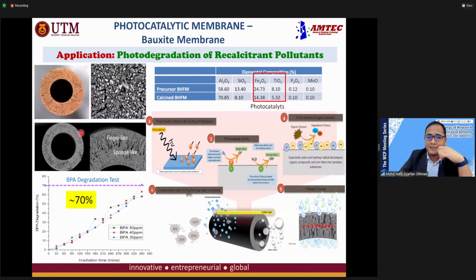It can also act as a self-cleaning membrane, because we know that membranes always have an issue with fouling. Organic pollutants, for example, settle on the membrane and block the pores. By using this photocatalytic membrane, we only need to expose it to UV or sunlight, for example, and it can degrade the cake layer, and we can reclean the membrane without any backwashing procedure. This is one of the good things about the photocatalytic membrane.